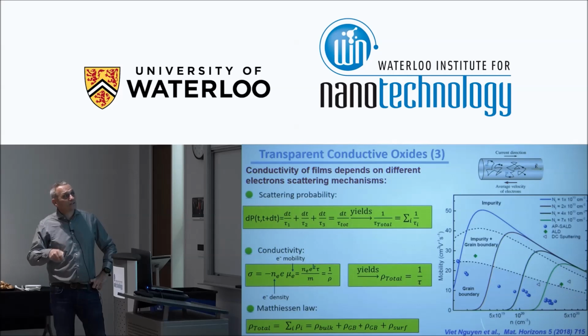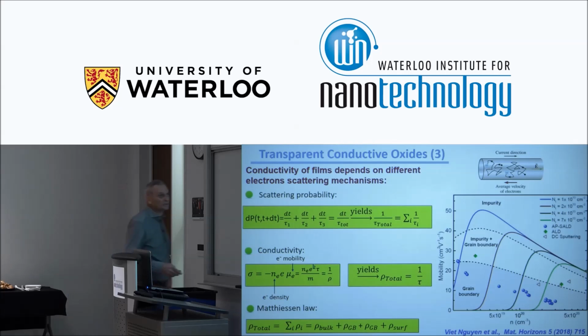And for example, here this is a recent article published in our lab where we plot the mobility of aluminum-doped zinc oxide versus the carrier density. And there are some conditions where the mechanism is more the grain boundary, and if not, it's more the impurity. And in this case, it's both of them, impurities and grain boundaries.